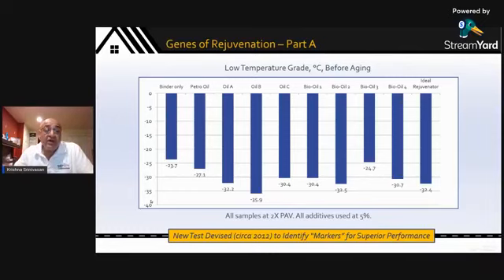And what we saw was we were getting different results until we decided in our lab to create artificial RAP, which means we synthetically aged our virgin binder, our virgin bitumen, in a lab oven to produce RAP binder. Now we have a highly consistent material to which we add 5% of maybe 30 or 40 different oils. We tried so many of them. And we still continue to do research to be able to, A, competitive benchmark, and B, develop more and more better rejuvenators.